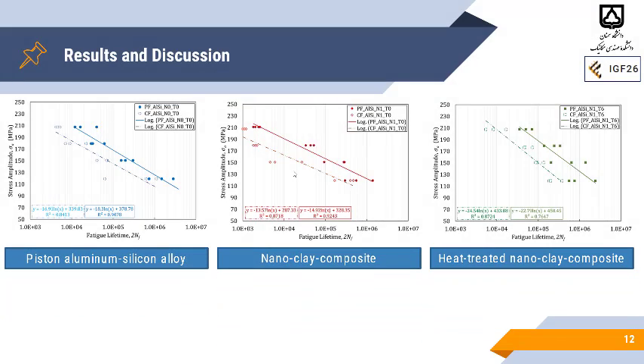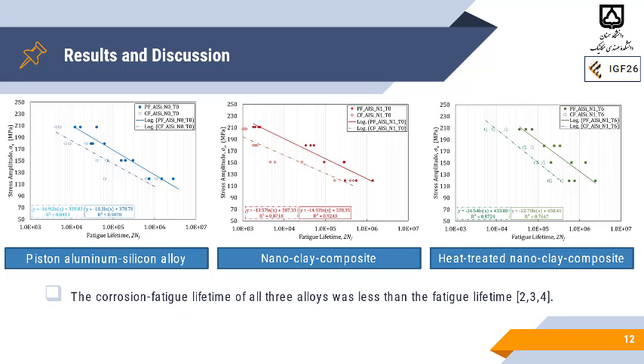For a better comparison, you can see here the pure fatigue curves beside the corrosion fatigue curves. The first figure is for piston aluminum alloy, the second one is nanoclay composite, and the third one is heat-treated nanoclay composite. Again, you can see a shift in all the results compared to pure fatigue. So the corrosion fatigue lifetime of all 3 alloys was less than the fatigue lifetime. Such behavior was also seen in the literature.